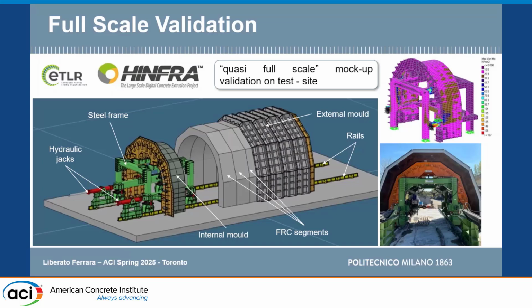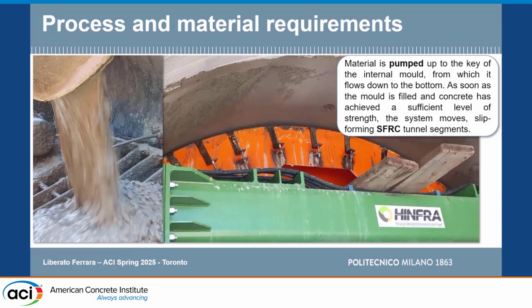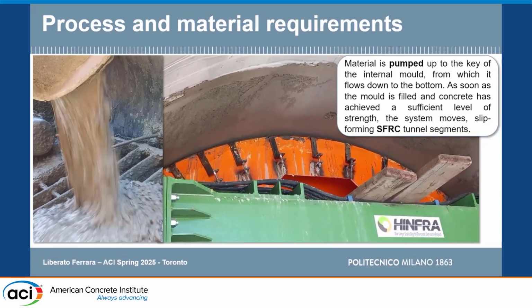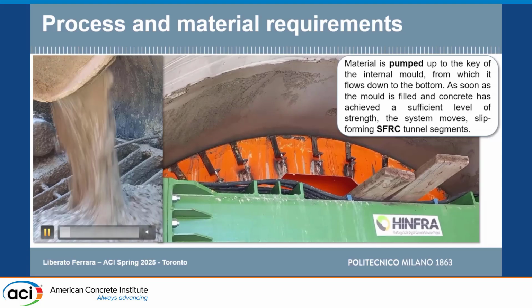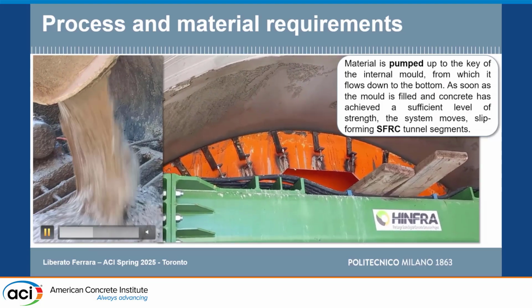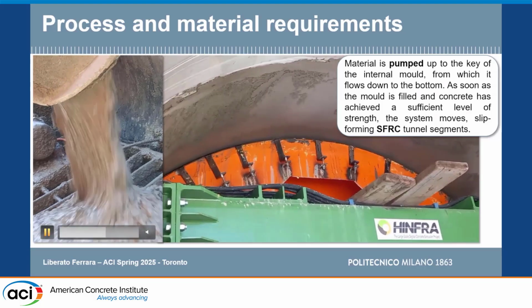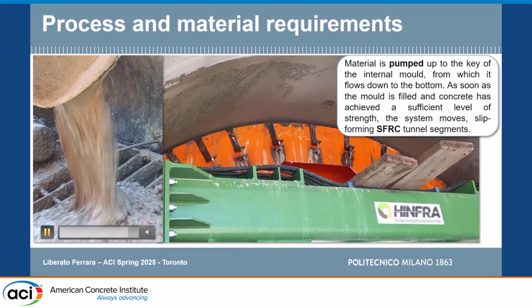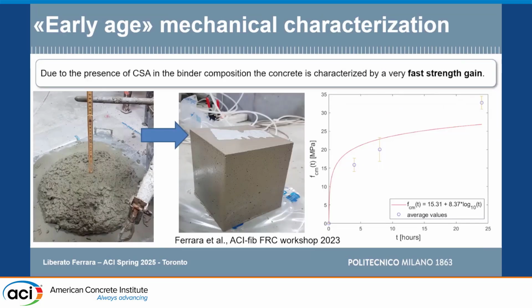There is a pumping circuit, you pump the concrete, and when it's ready to be slip formed, you go from this. You can see the slip forming machine is moving, and I hope this movie works as well. So in a very short time frame, which is about a couple of hours, we must go from a self-compacting mix, which has to be pumped, to a mix which is self-standing.